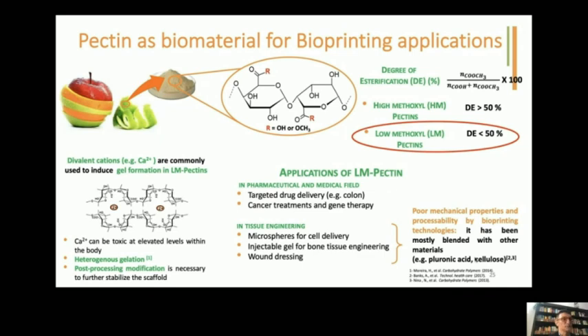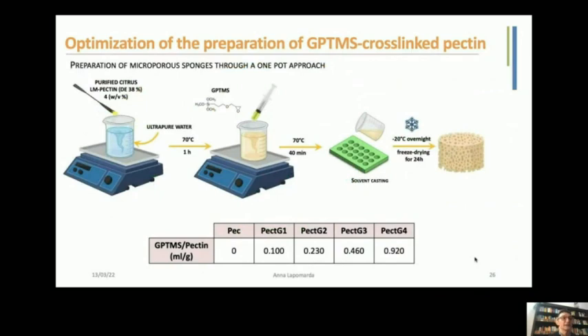And we tried to use another typical approach. Initially, we started to create scaffolds, principally sponge scaffolds, so a random structure, just mixing the pectin dissolved in water. Then we added the GPTMS. We heated it in order to create a perfect solution. Then we cast it. We induced a freeze-drying process for 24 hours, and we obtained a porous scaffold.